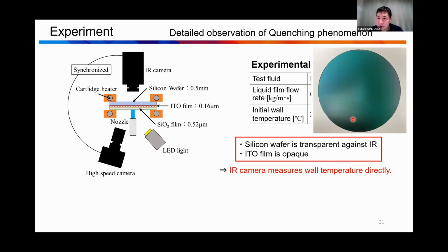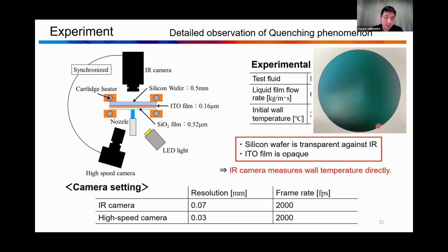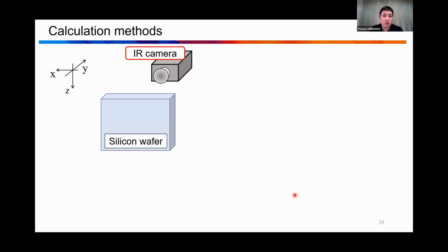So this is the actual image of the high temperature wall, and we added an oxide layer on the surface in sequence. Okay, the camera setting is the same. We try to use the same frame rate here, 2000 and 2000, completely synchronized between the infrared camera and the high-speed camera. Okay, so the next one is the calculation method.